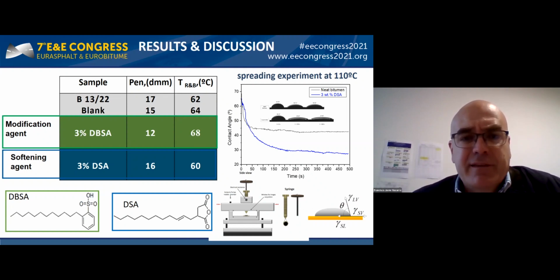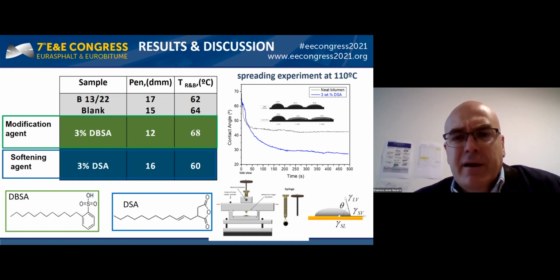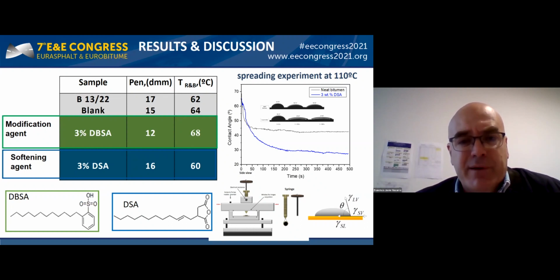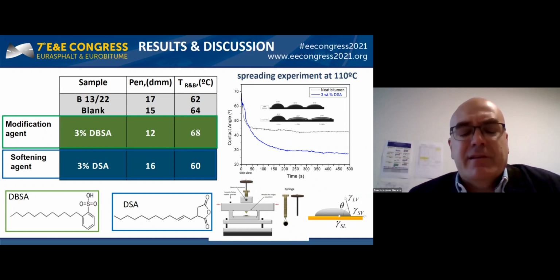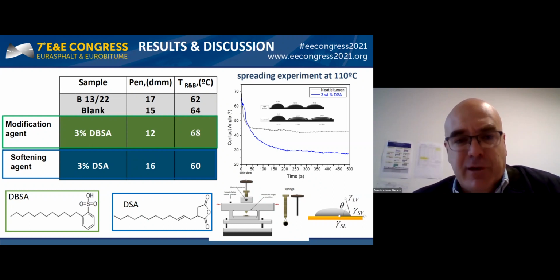As presented here, this table shows us how the hardening of neat bitumen is produced after the processing of the sample. This table also illustrates that reactive surfactants exert a quite different modification of the technological properties. Then the addition of dodecyl benzene sulfonic acid, DBSA, leads to a decrease of 3 tenths of a millimeter in the penetration and a clear rise of 4 degrees in the softening temperature.